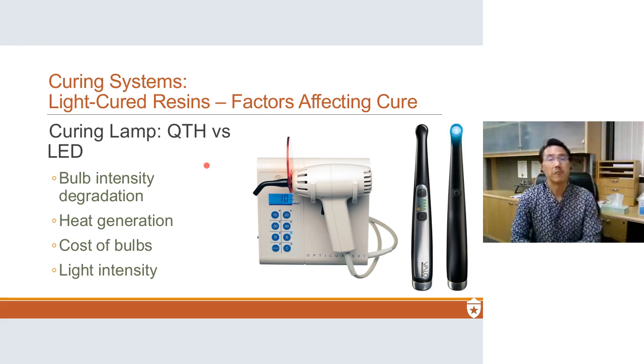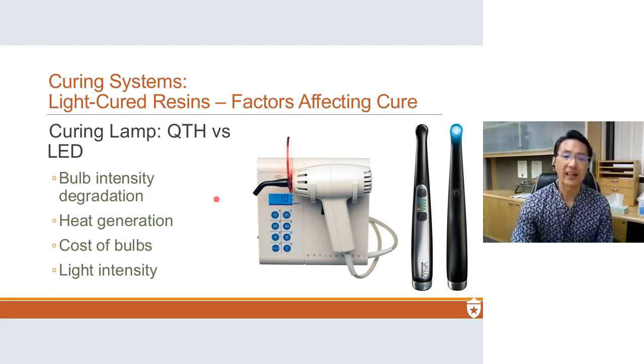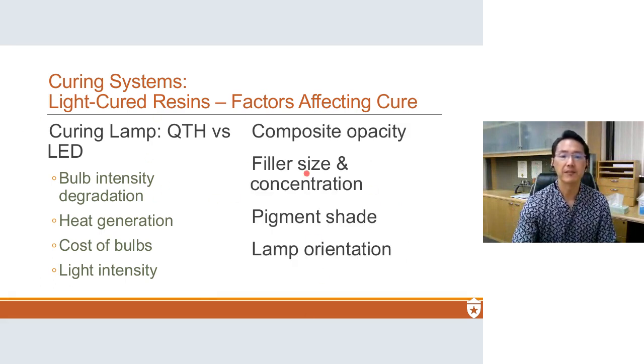So generally, QTH lamps are about 400 milliwatts per centimeter squared, I think it is, and the LEDs are like 1,000 and above. So it's much stronger than the halogen lamps. Okay. So this is an LED lamp. This is a halogen lamp. Some other factors affecting the cure, again, the opacity, the filler size and concentration. Okay. Because the more you have, the more difficult it is to cure, because there's a mismatch between the index of refraction of the particles and the resin, and that causes opacity. Okay, so the more filler you have, the more opaque it gets. Shade, we talked about that, and the lamp orientation.